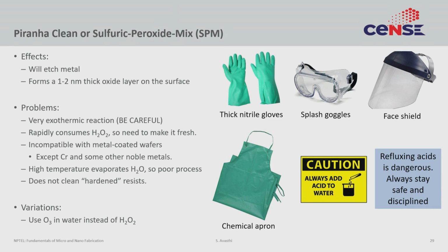The larger the batch, the more heating up. The other thing is this mixture actually rapidly consumes the H2O2, so it releases the oxygen. So you need to make this a fresh solution every single time. You can't make a batch and then keep it and use it over a week. It has to be made fresh right before the experiment, or at least the first thing in the morning. And it is active for some variable time, say half an hour, 1 hour, something like that.